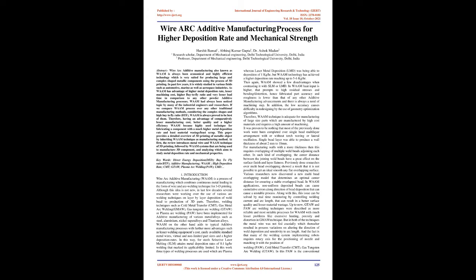In this way, for steel, selective laser melting, SLM, attains metal deposition rates of 0.1 kg/hr, whereas laser metal deposition, LMD, was able to deposit 1 kg/hr, but WAAM technology has achieved a higher deposition rate reaching up to 5 to 6 kg/hr.